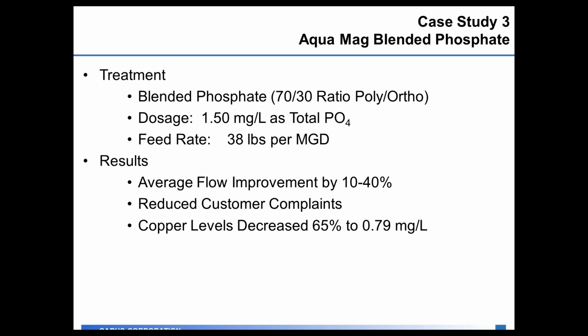One of the things they looked at, because hydrant testing showed flow issues in the distribution system, is the flow improvement from those hydrants after the application of the Aqua phosphate. Depending on the hydrant they were testing, they saw anywhere from a 10% to a 40% increase in hydrant flow rates through those hydrants after applying the Aqua phosphate.